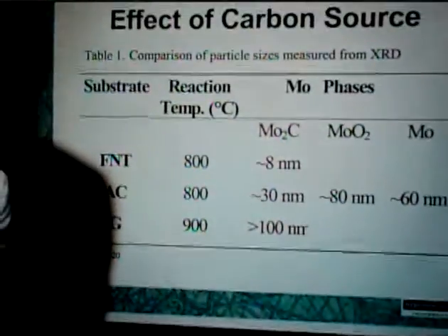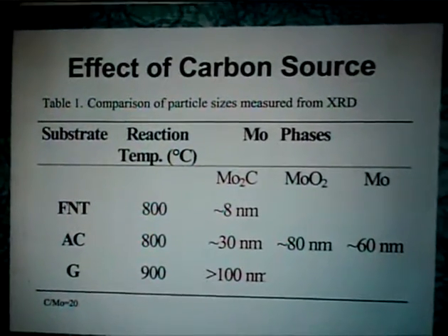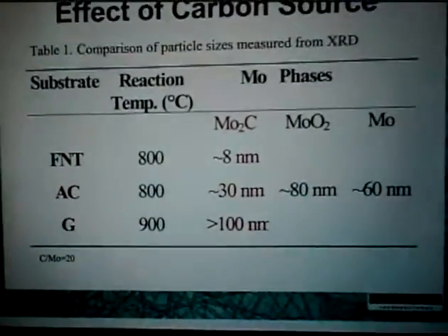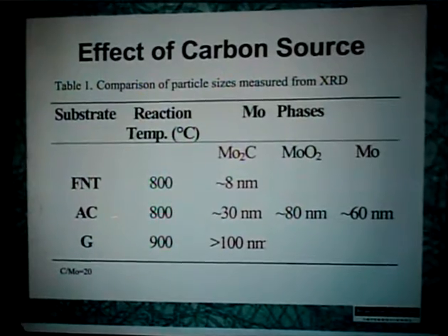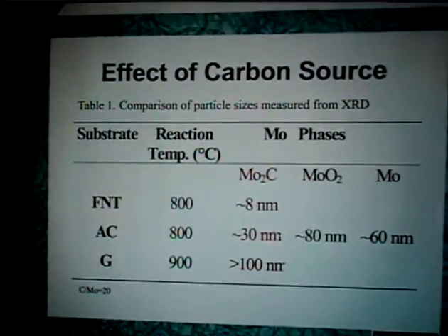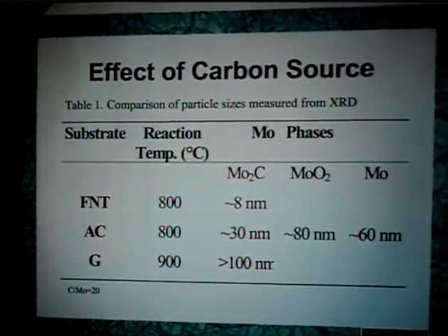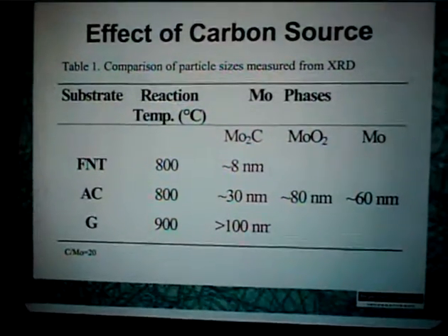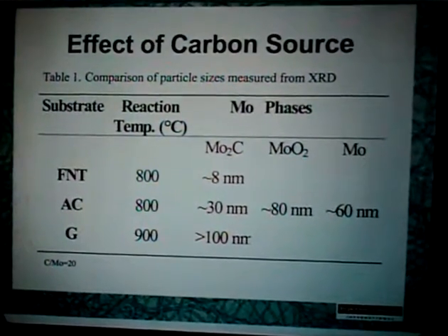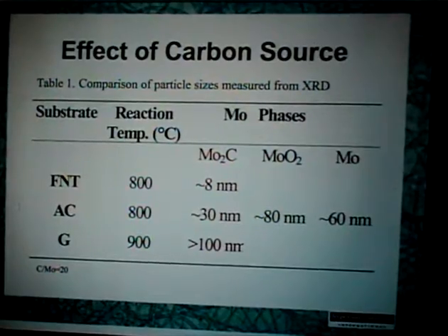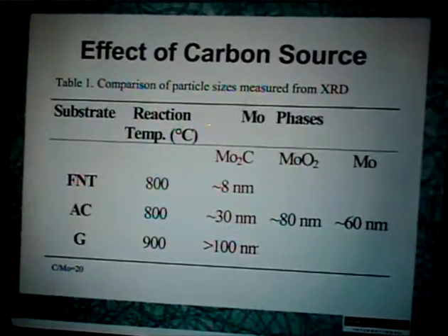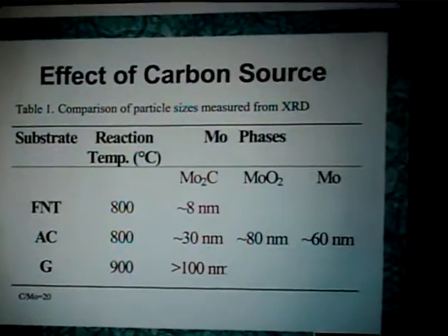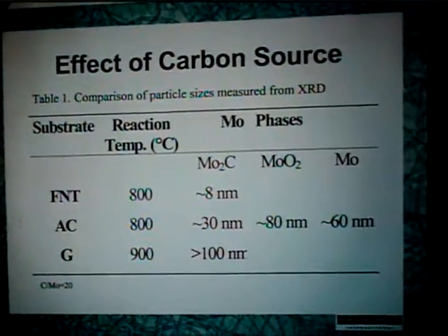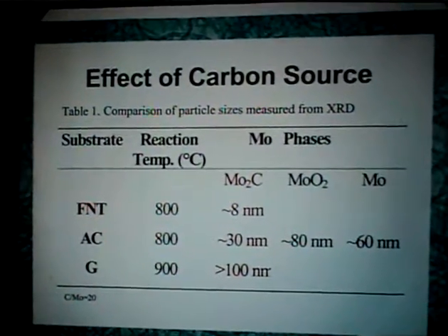So if you use X-ray diffraction to look at what we have, here's the reaction temperature. The molybdenum carbide phase on the carbon nanotube is about 8 nanometers. On the activated carbon, we actually got a mixture of things and pretty large particles of molybdenum carbide. And on the graphite, we also got a very large phase of molybdenum carbide. But of course, we are making the preparation in exactly the same way for the purpose of comparison. Of course, you can prepare molybdenum carbides many other ways. Using this activated carbon, you can optimize it by preparing it in different ways.